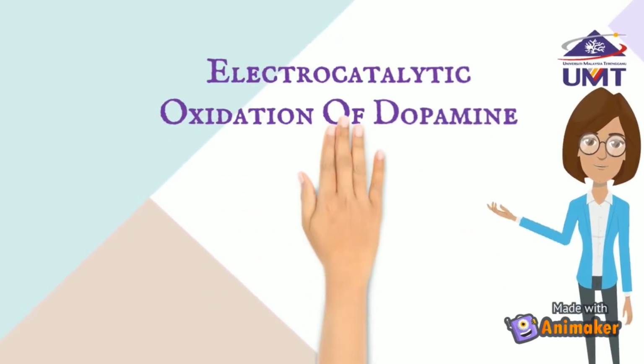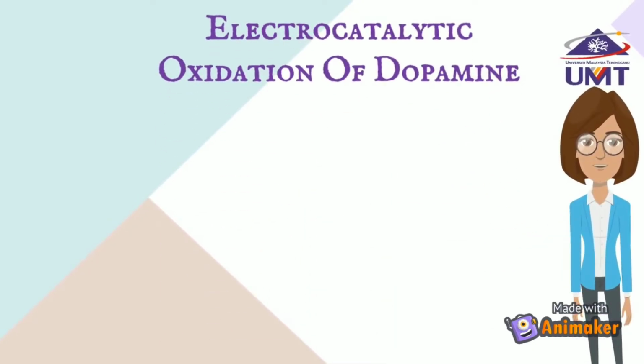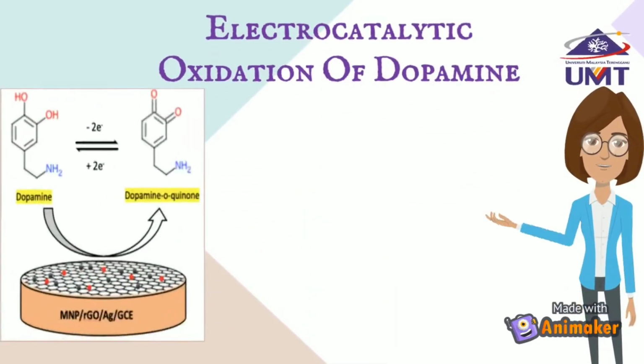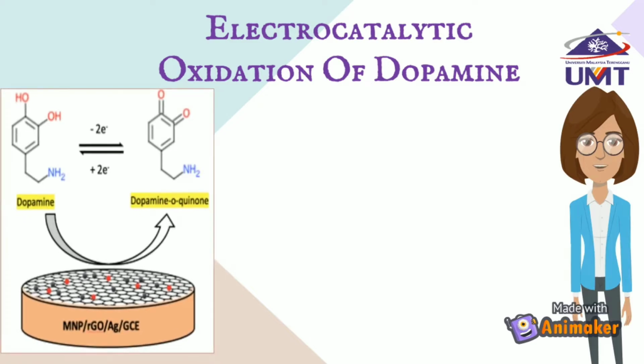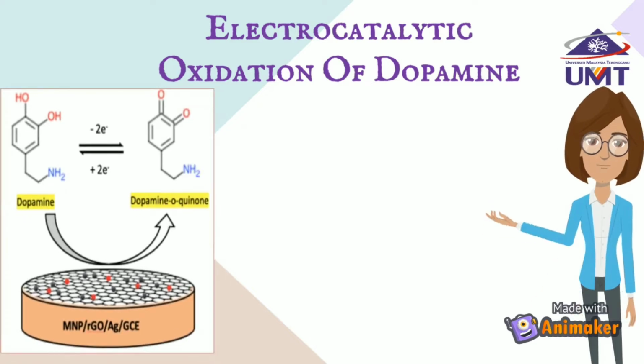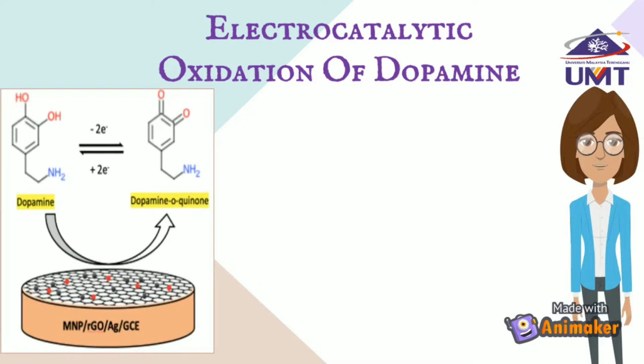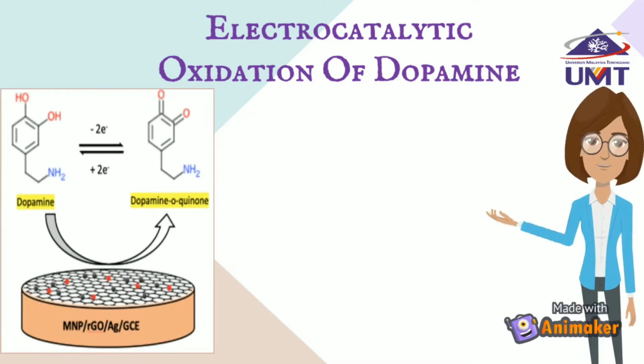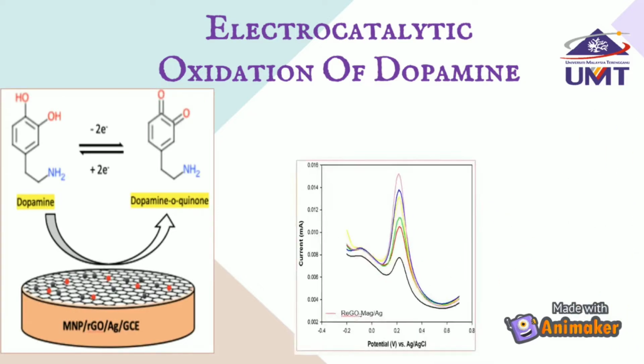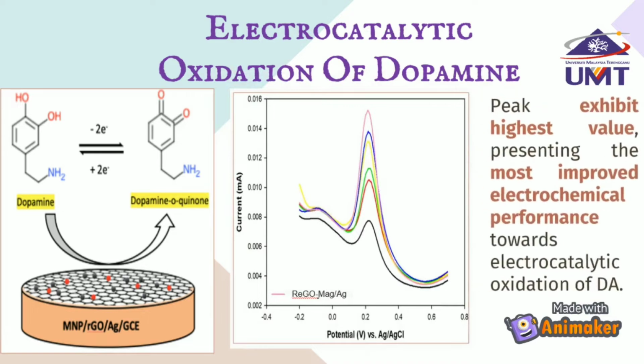Moreover, for the process, the electrochemical method was conducted. Dopamine undergoes an oxidation process, oxidizing from dopamine to dopamine-o-quinone. Electrocatalytic oxidation of dopamine was done on the reduced graphene oxide magnetite silver electrode, and the results exhibit the highest peak value, presenting the most improved electrochemical performance toward electrocatalytic oxidation of dopamine compared to other unmodified electrode sensors.